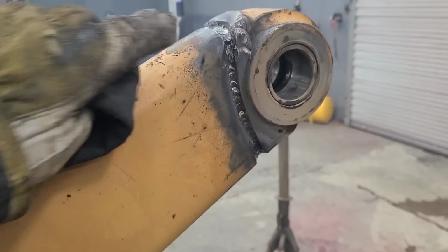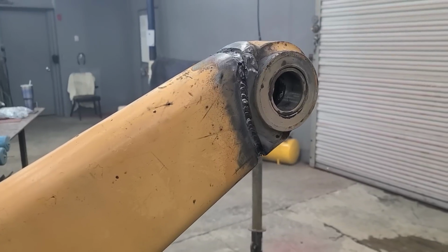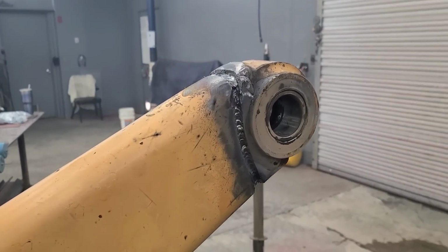So when I grind those bumps from a lumpy start or from anything that's lumpy, I grind it in a way that I'm kind of trying to make a ramp instead of a cliff where we could have slag stuck at the bottom of the cliff. I'm trying to make a ramp so that when I'm transitioning from this weld on the side to the weld on the top, it's a smooth transition without any deep places where slag can remain.